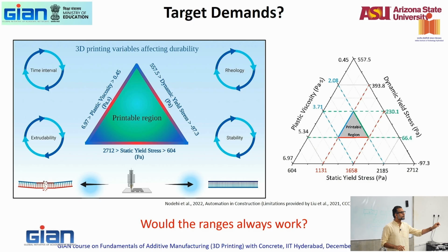So you can use the paste qualities. I have a plastic viscosity of the paste that goes in because I really can't measure the concrete. You have concrete rheometers available, but it's very difficult. The variability in concrete viscosity measurements is extremely high. So you do the paste measurements, you do your concrete mix or a mortar mix, and you can do mortar rheology too. Not that difficult. All these measurements you can do on mortar sands also. But if you want to do concretes, you can do this mortar rheology.